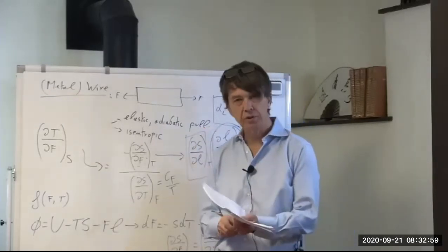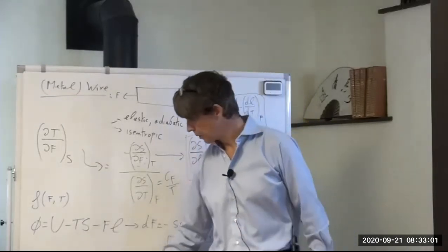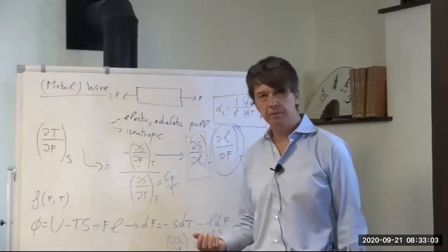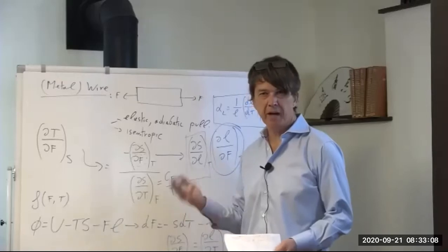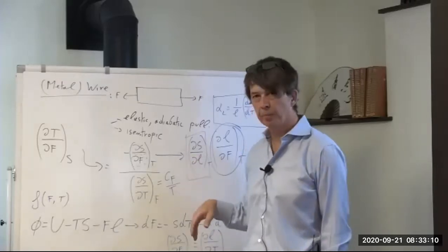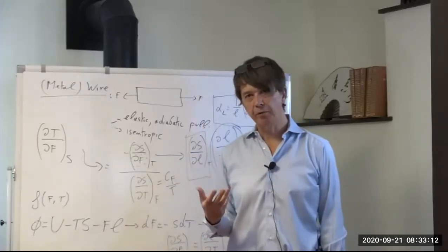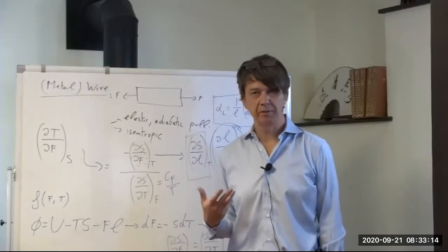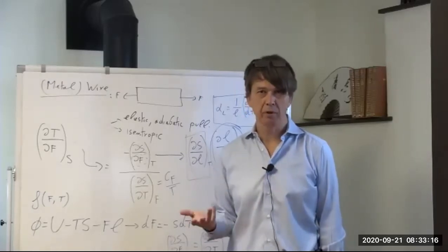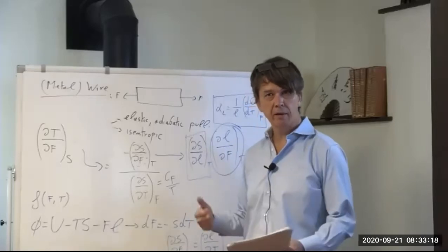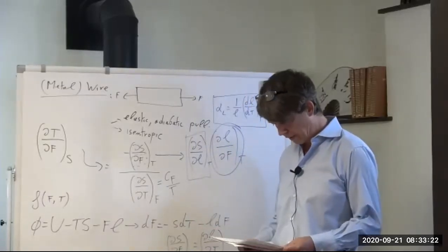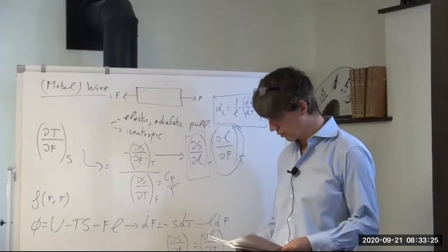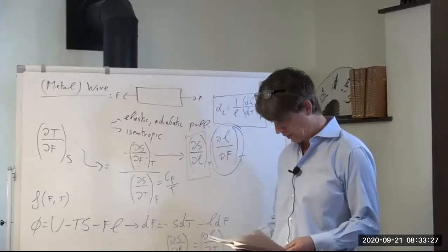What happens to this entropy derivative? So for most materials, if you make the volume bigger, the bonds get softer, they vibrate more, they disorder more, you get higher entropy. But as many of you have seen before, for a few materials, that's actually different. And polymers and rubbers are, for example, in that category. There, if you stretch them more, their entropy goes down. And we'll come back to that example, maybe later in the lecture, or probably at the next lecture.